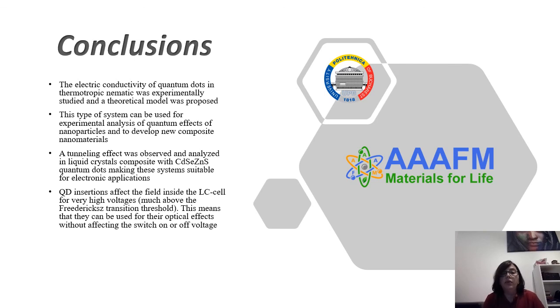And as a final conclusion, quantum dot insertion affects the field inside the LC cell only for very high voltages, much above the Freedericksz transition threshold, which means that they can be used for their optical effects without affecting the switch off or switch on voltages. So they are promising composites for many applications and we hope in the future we can obtain more data about this kind of nanoparticles.